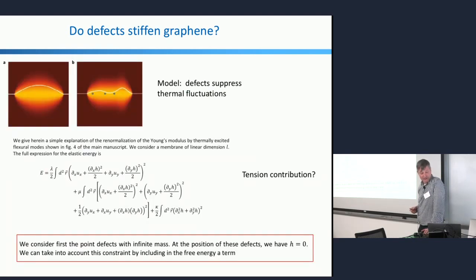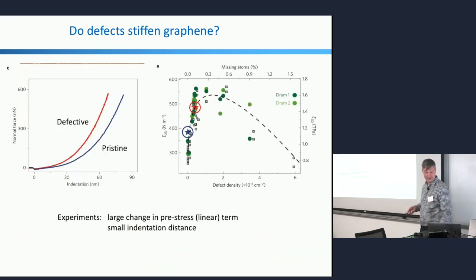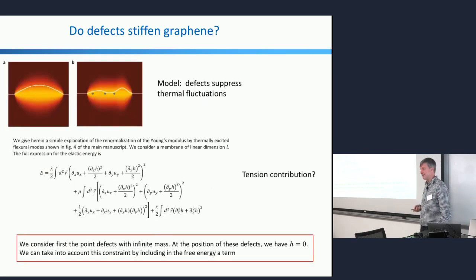If I look at the theory, and please, Boris and others, join in here, right? The idea is that there are thermal fluctuations in graphene at room temperature. And the model was to say if we put in defects, those suppress the thermal fluctuations. And there are a couple of really funny things I see with this theory. One is that they write the energy of this membrane, ignoring all the other terms here, but there's no contribution of tension to this energy, which is fine, maybe in the unstressed case, but again, even here they're showing there's a linear term, so there is a built-in tension, which they seem to ignore in the theory altogether. And certainly at high strain, the tension is a dominant contribution to the energy.